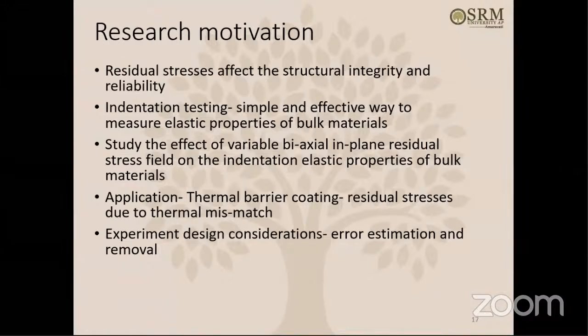The motivation and background: residual stresses affect structural integrity and reliability. Indentation testing, of course, is a simple and most effective way to measure the elastic properties of bulk material. So what exactly do we do? We study the effect of variable biaxial in-plane residual stress field on the indentation elastic properties. How do you create this biaxial field? That also we'll see. Applications include thermal barrier coatings, residual stresses due to thermal mismatch, and experiment design considerations.